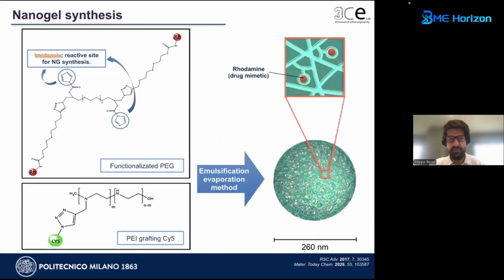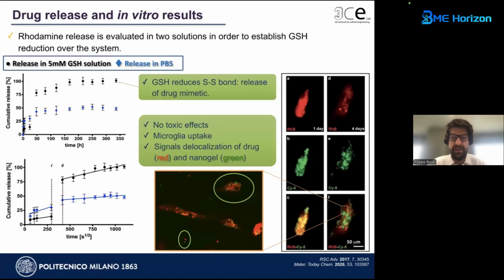We made the same nanogel, and then with some post-polymer functionalization strategy, we loaded here a drug mimetic to see if it can work or not. So basically, what you can see from the cumulative release on the left is that the presence of glutathione increases the release of the molecule. So again, it is able to cleave and release, in this case, the drug mimetic, also from the cells. This was also looking at the delocalization of the drug on the nanogel in the picture on the right. We have to be honest that this possibility to link a drug is very interesting from an academic perspective, but extremely more difficult.